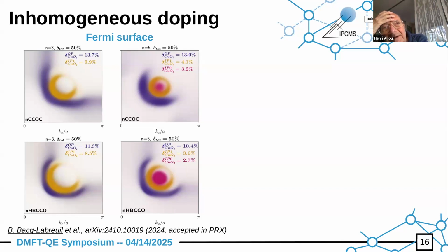My question is rather: what would occur for single layers? That is, in some sense, this inner layer, is it really in the same situation as a single layer, in some sense, less doped? Yes. As far as we can tell, the inner layer seems to behave quite similarly to the outer planes, but less doped. Although there is this small subtlety that the correlation seems to be slightly weaker in these. This is what puzzles me, because you say that correlations are weaker, but still you would be in the pseudo gap regime because the doping is small.